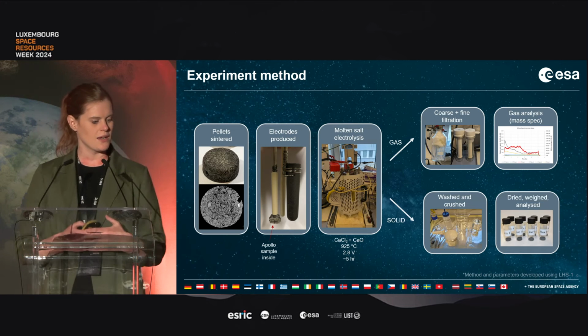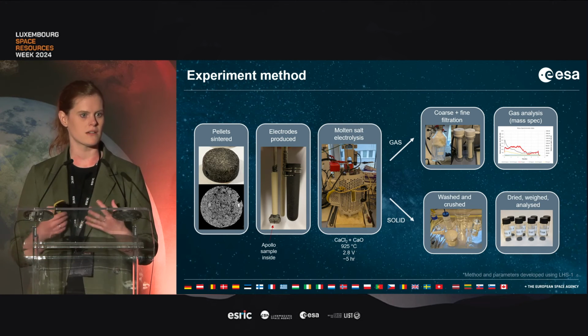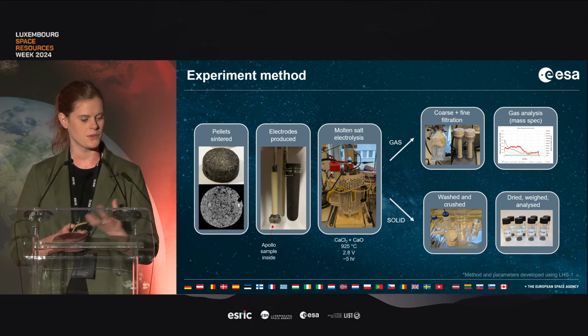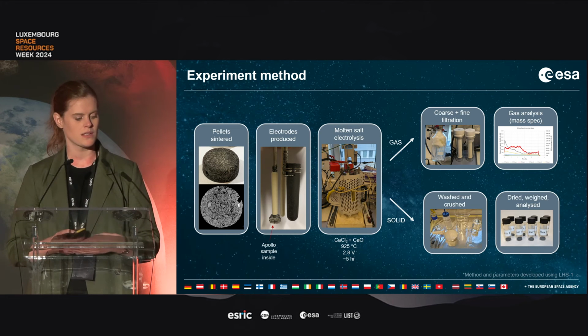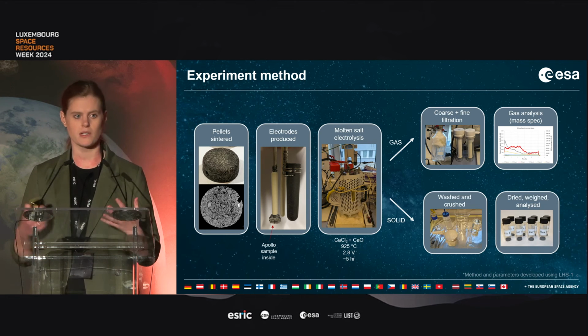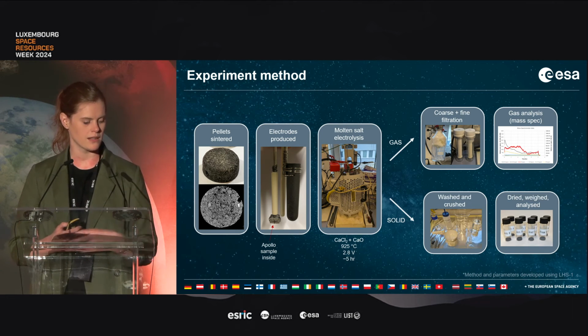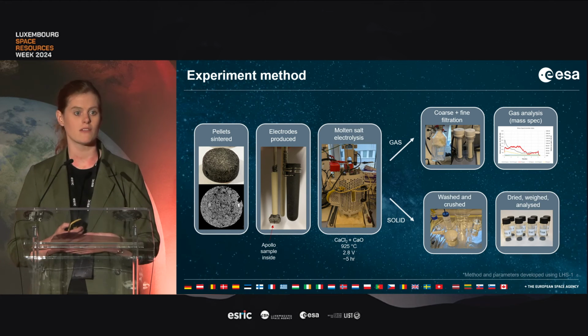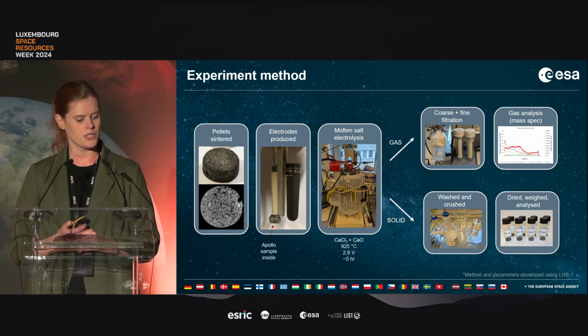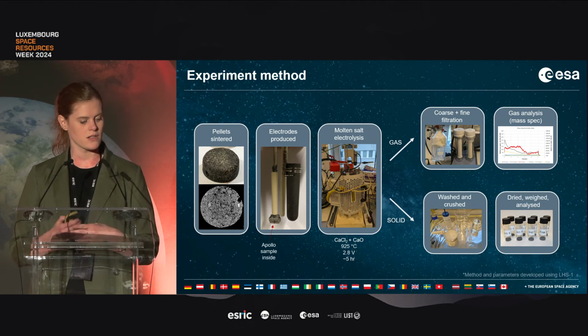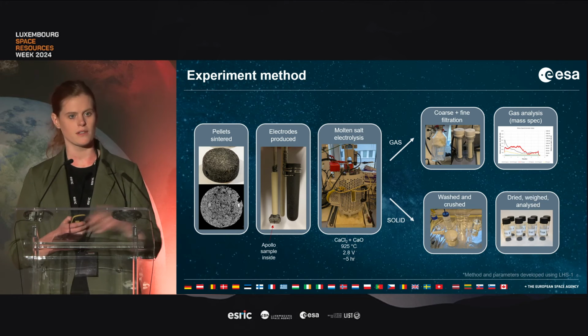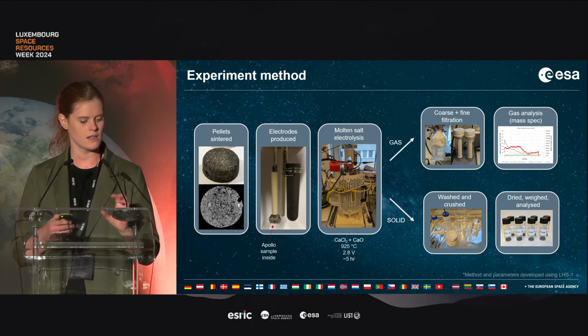So onto the experiment method. We first sintered the material, the powdered Apollo samples, into small pellets. So this was primarily to not lose it in the salt if we'd left it in the powdered state, to try and make a really cohesive block. We then produced these kind of small electrodes. The Apollo sample you can see is inside that tiny metal basket.